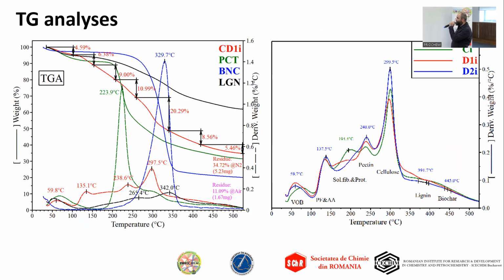Thermogravimetric analysis allows the evaluation of the sample based on the thermal decomposition into specific fragments. In this case, we compare the cabbage sample with the degradation of pectin with onset temperature around 224, cellulose with an onset temperature around 329, and lignin around 340 or 400.